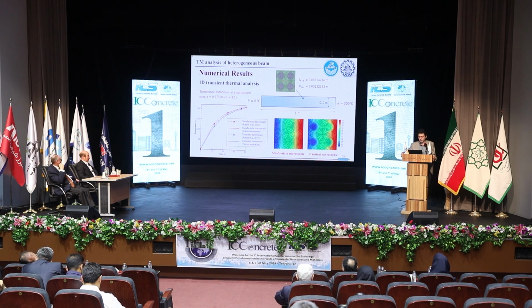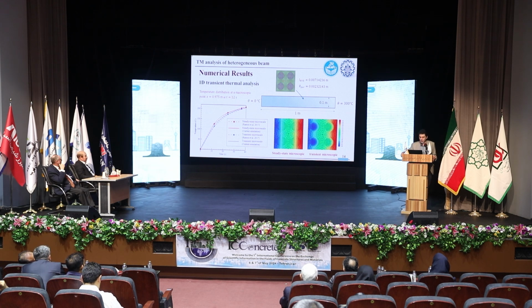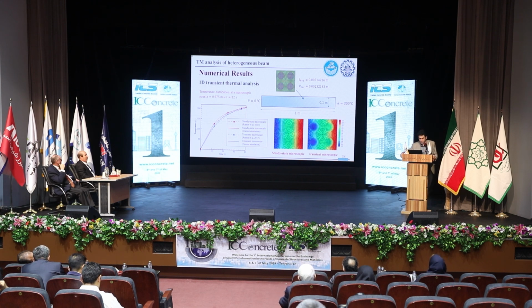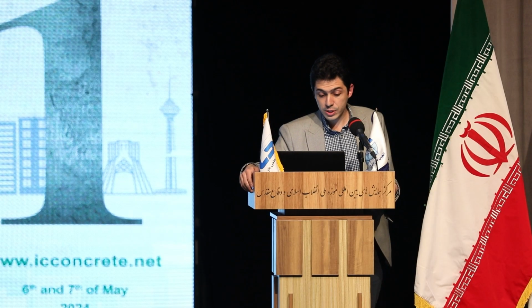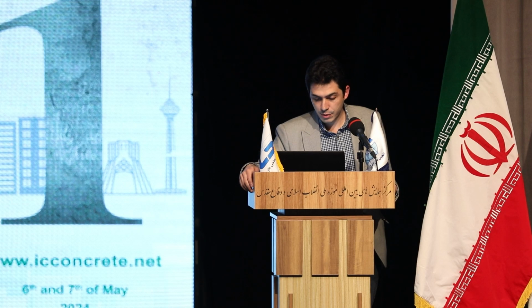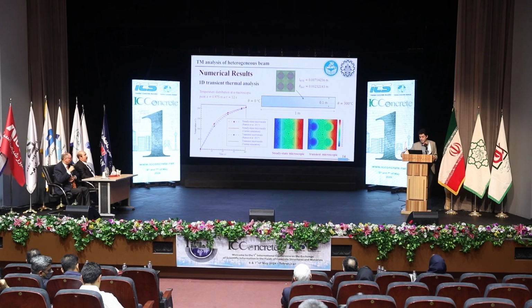We have chosen a heterogeneous beam, a benchmark problem composed of fibers embedded inside the matrix, which is shown at the top of the screen. This beam is loaded thermally and mechanically on its right edge, and we have solved it with our proposed multi-scale method. The results are in good agreement with the results reported by the reference, and we have also shown the transient effect captured by our method in the bottom right side of the slide, in comparison to the steady state solution.